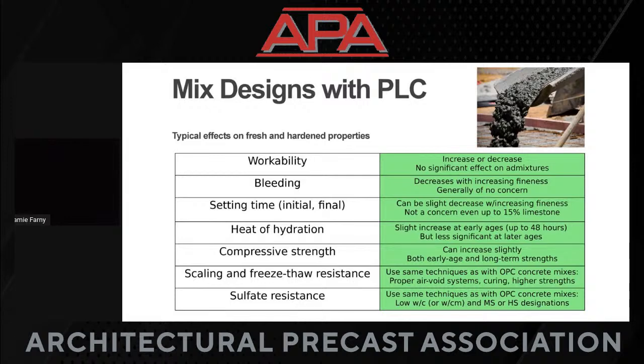Compressive strength, both the early and long-term strengths, can increase. And it goes back to that slide about the particle packing, the nucleation, the slight reactivity when we grind limestone so finely. So strength is actually something that's pretty well figured out.